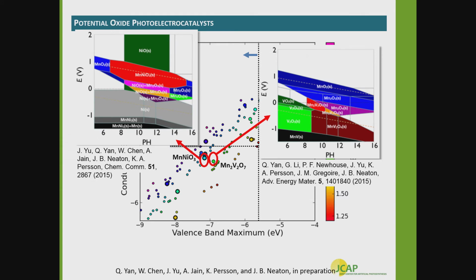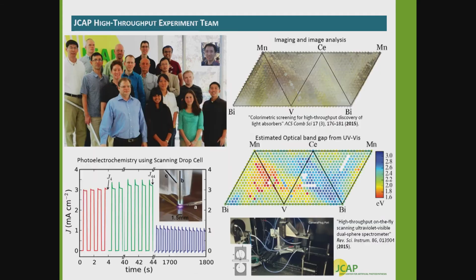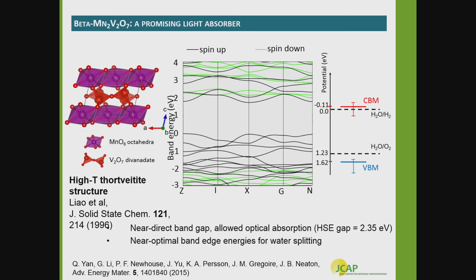And pursuing further the work on the manganese nickel oxide and manganese vanadium oxide, we found that the manganese vanadium oxide exhibited stability under electrochemical operating conditions for OER catalyst and for photoanode electrolytes. And the high throughput experimentation team swung into action to look at the generation, using combinatorial synthesis methods, of a whole range of possible ternary alloys, including component elements manganese, vanadium, bismuth, cerium, and zeroed in on the bismuth, the manganese vanadate class. And the theoretical team was able to, using the hybrid density functional theory approaches, find that the